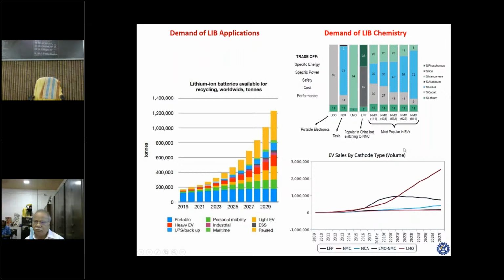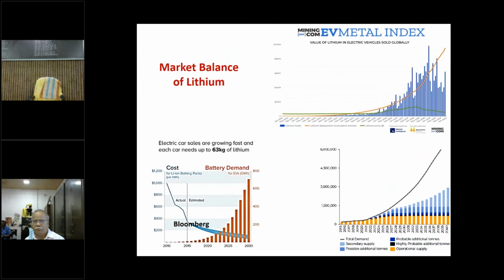So if you're able to have a 1:1:1 ratio of lithium nickel cobalt manganese, which is categorically not possible, you can actually substitute by increasing the nickel and manganese concentration and decreasing the concentration of cobalt, and this would actually be helpful. In the forthcoming slides, you will come to know the role of each metal in these batteries. Now I would come from the chemistry to the market balance, because if I have more cathode, what is the kind of sales for me?